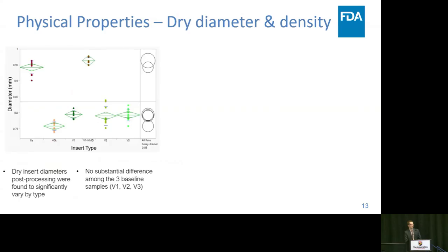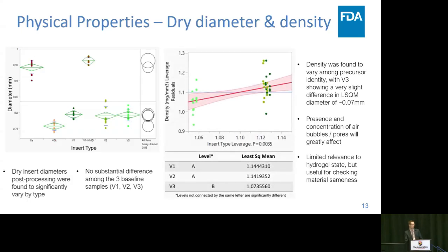We observed some differences with the 8-arm and with using non-micronized dexamethasone instead of micronized dexamethasone. We noticed that those caused a greater diameter on average post-processing. But between the other polymers, the 3 variants that we looked at, there was no substantial difference. There was actually a difference in density for the V3 polymer, which had basically poorer functionalization than the other 2. And we noticed that this resulted in a slightly lower density.